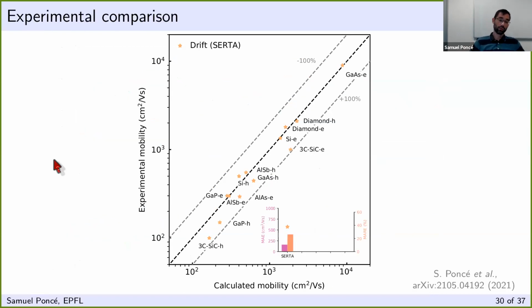So now we can ask, how accurate are our predictions or calculations with respect to experimental data? Here I'm showing the comparison between the calculated mobility versus the experimental mobility. And this is the drift SERTA mobility. As you can see, the comparison with experiment is not too bad. We are typically overestimating a bit, but not too much. This is the mean absolute error in percent, and we overestimate a bit.